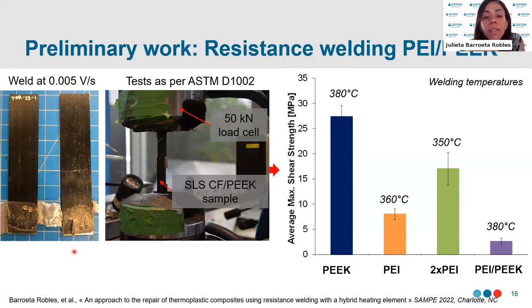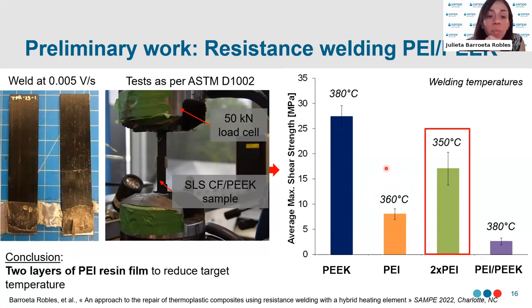We can see the results in the slide, and we see that the baseline, which had PEEK resin film, attained strengths ranging from 25 to 30 megapascals, which is roughly what we expect with this type of material. But when we compare the case of using a PEI resin film, we saw that we needed to target a temperature above the melt temperature of PEEK, and a significant decrease in the performance. However, what was promising from that work was that using two layers of PEI on each side improved the results, and we were able to reduce the target temperature by 10 degrees. These results infer that using this extra layer of PEI resin film improved the resin content and also improved the thermal and electrical insulation at the weld. And finally, we see that using the hybrid heating element did not yield a high mechanical performance despite targeting the processing temperatures of PEEK.